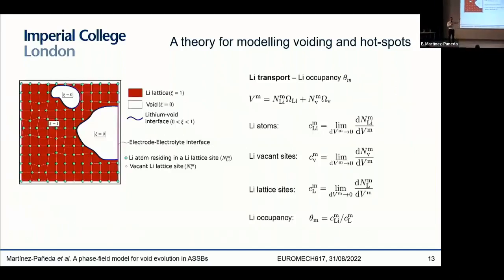I'm going to start by focusing on the anode only. So the anode basically has two regions. There's the voided region, and then there's also the solid phase region. And within the solid phase region, we can talk about the lithium transport, the lithium occupancy. We can assume that the lattice sites are going to be either occupied or vacant. And if we do so, then we can define a lithium concentration, several concentration measurements, and a lithium occupancy, which is going to be our primary field for the transport problem.